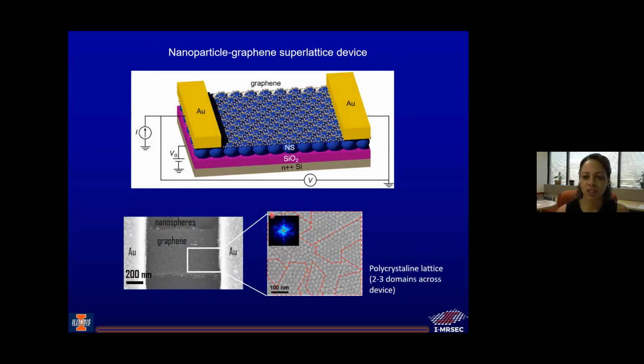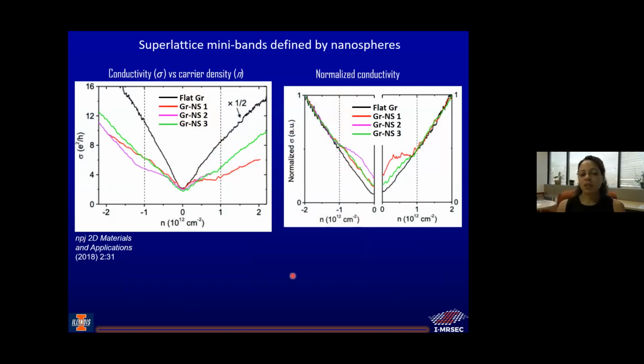But if you do a Fourier transform of this, you can still see that overall you get a quasi-crystalline structure. Okay, so in case you're worried that it's all disordered, it's not very disordered. You can still get quasi-crystalline. Okay, so we have this device. Again, the scale of it is about a micron across. And now we measure the conductance. And so this is conductivity as a function of carrier density.